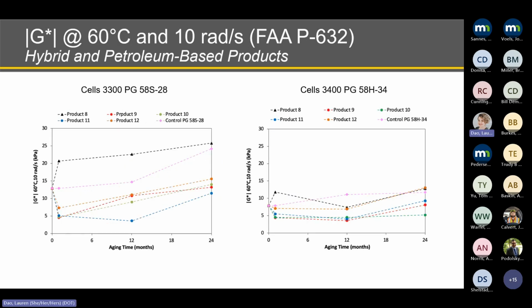Same comparison now considering the petroleum-based products, where on the left side graph, we have results considering the PG 58S-28 binder, and on the right side, the PG 58H-34. Again, we see that the response of these products differs based on the binder present on the surface of the pavement, and that what is captured after 1 month is not really the actual response on the long-term performance of these treatments.